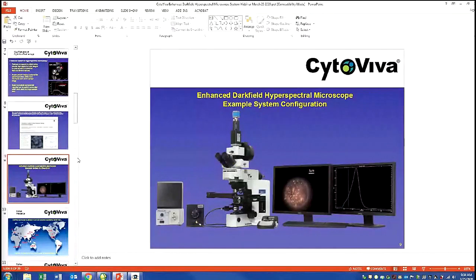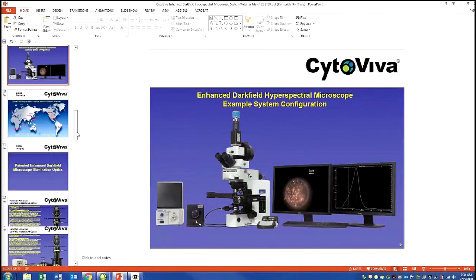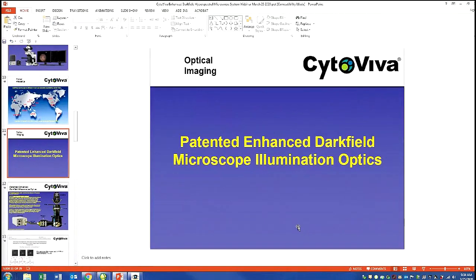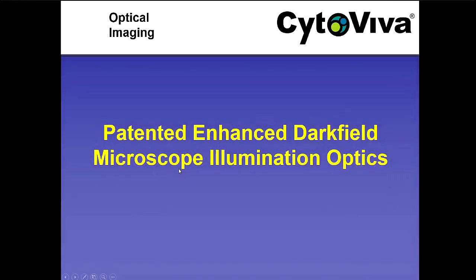But if we go on an area here where we may have an aggregate, we're going to see what looks like two nanoparticles that have joined together and have become a rod. If you see this blue spectrum here, the main peak seems to shift over here and redshift to about 650, about 100 nanometers redshift. But there's still a shoulder over here at this 560 nanometer wavelength range, which is indicative of the first two. We just wanted to show you what nanoparticles themselves look like in solution when they're not in a sample and image.